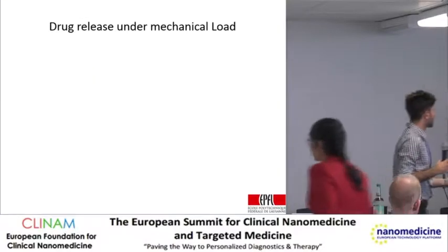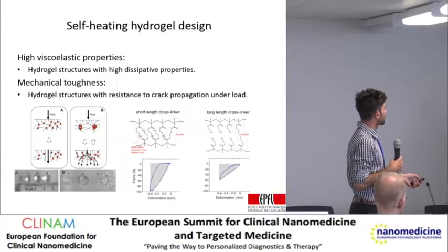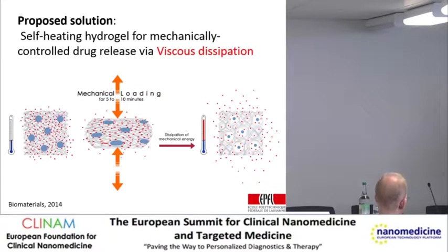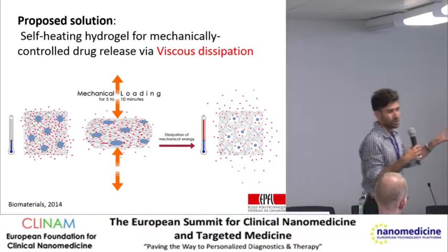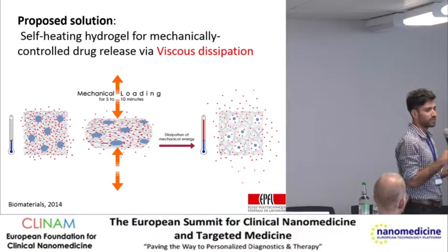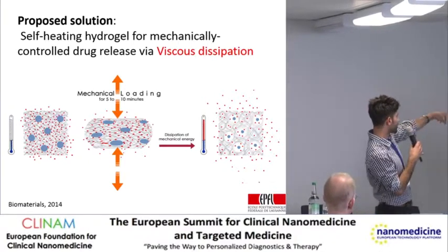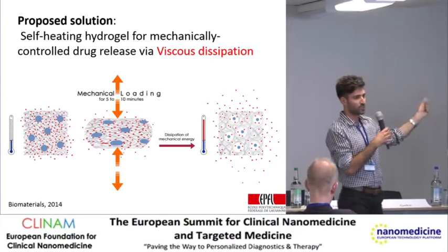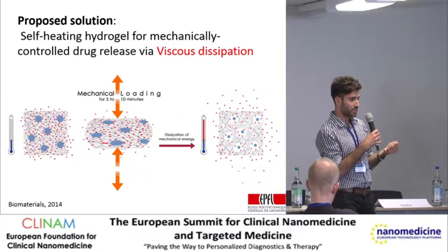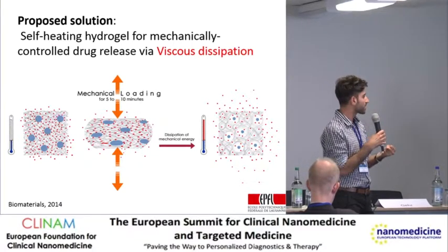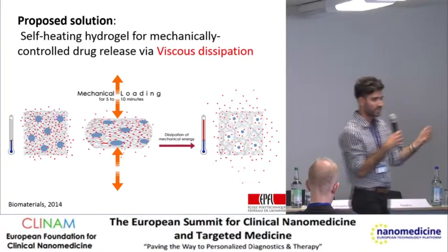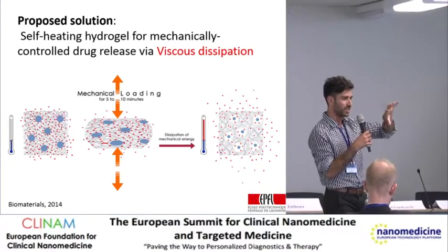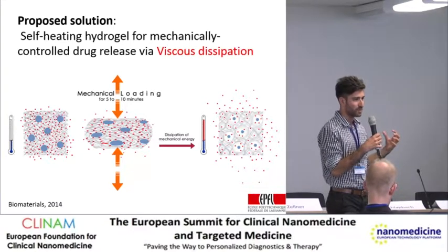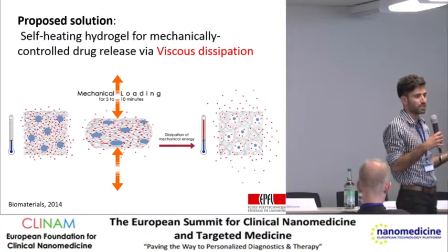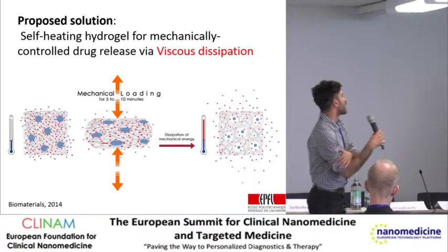So the gel, as I told, maybe I should show this slide again. This one. The gel is really a gel with very low permeability. So at normal temperature, you don't have a lot of release. But the nanoparticles that we used, the idea was that when the temperature reaches, for example, 37, they shrink suddenly. They become hydrophobic actually. So they shrink, and when they shrink, as you see in the last picture, they occupy much less space. So they provide open space inside the gel, like interconnected open space, and they increase the permeability of the gel because the mesh size of the gel kind of increases in this way. What material is it?